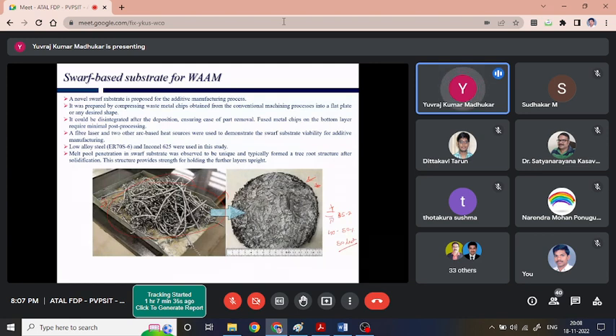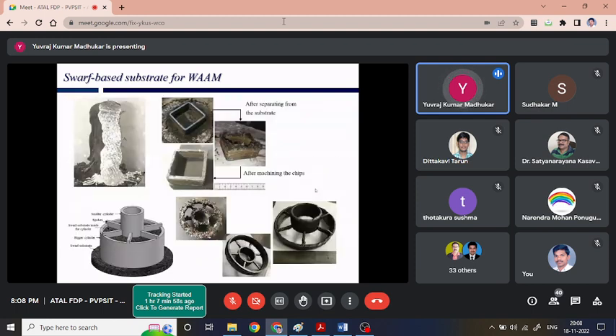Basically we collected the metal chips and compressed them in order to make a plate which has basically a porous structure. Now since these metallic chips have a lot of edges on them, while compressing, they interlock with each other, so they won't disassemble so easily. Since it is made of metallic chips, we can use it for additive manufacturing applications. Again, making the arc stable between this chip base and depositing on it is certainly going to be very, very challenging. However, it is feasible. We could achieve it.